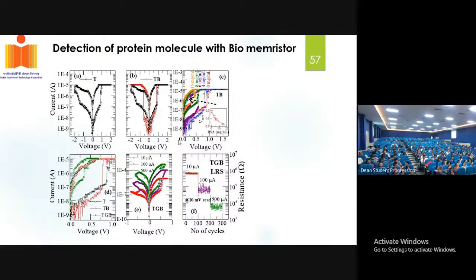So these are the IV characteristics that we have obtained. As you could see here, we try to attach the BSA protein to the device. The more BSA protein that we attach to the device, the lower the switching voltages. Which essentially means that as you attach more and more BSA protein to the device, the voltage at which the device goes from high resistance state to the low resistance state is decreased, as you could see from this arrow mark. Okay, so it is decreased to the lower voltage. Which essentially means that our device is sensitive to detect the biomolecules.